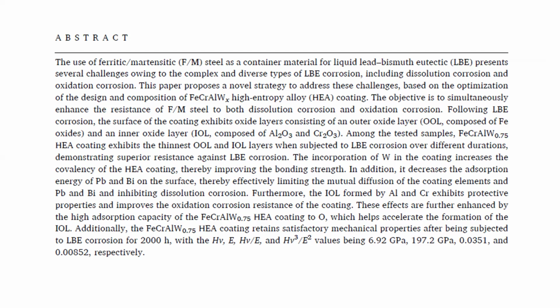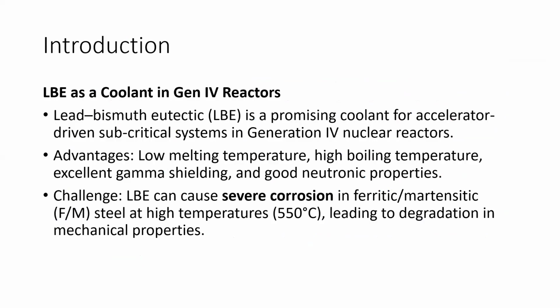the IOL. Additionally, the coating retains satisfactory mechanical properties after being subjected to LBE corrosion for 2000 hours, with HV, E, H/E, and H^3/E^2 values being 6.92 gigapascal, 197.2 gigapascal, 0.0351 and 0.00852 respectively.